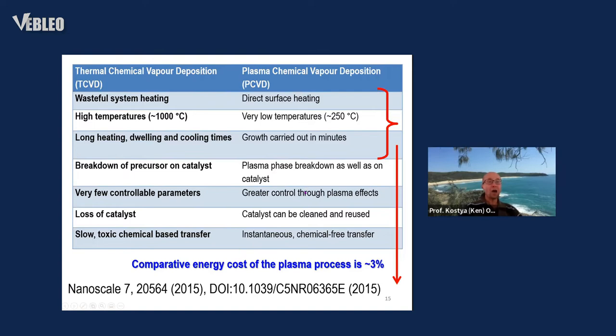Faster processes and better control, and as already shown, the separation of the grown structures from the catalyst using water without any chemicals. And a very interesting thing, the ability to reuse the catalyst and grow those nanostructures using plasma on the catalyst again and again. And energy cost-wise, it's very important that the cost of the plasma process, because it's faster and it's efficient, can become as low as just 3% of comparable thermal processes that produce similar types of nanostructures.